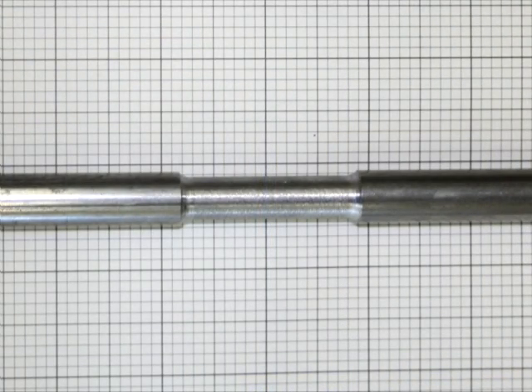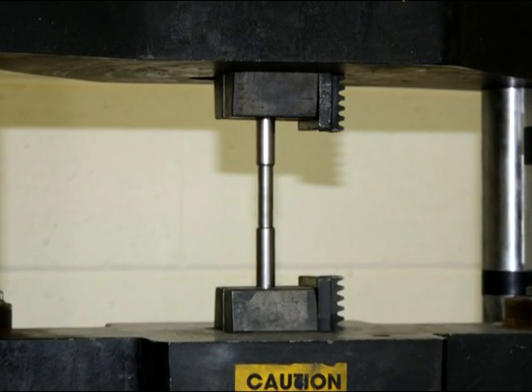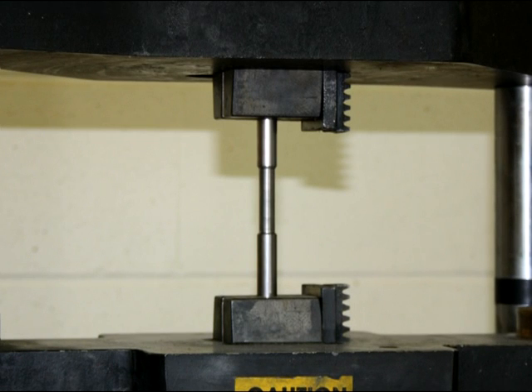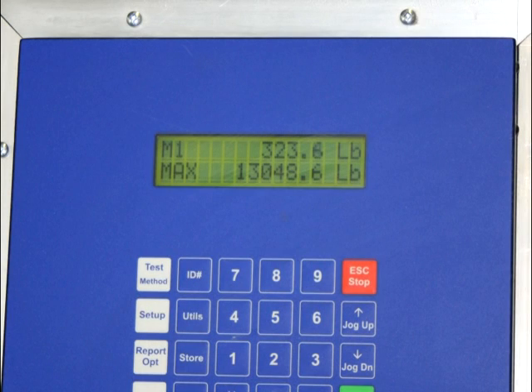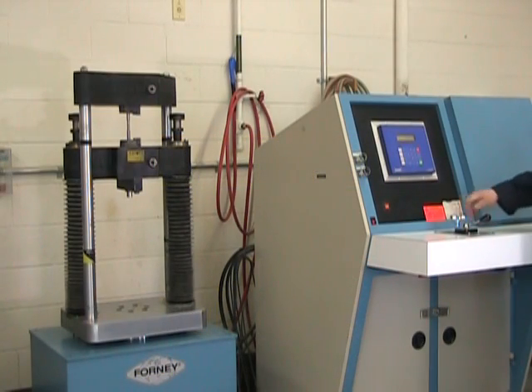Our test part here is a necked and accurately turned piece of mild steel. It's necked or reduced in diameter so that we can predict where the rupture will occur. And its diameter is accurate to help us with our final calculation. In this case, our test piece measures 399 thousandths of an inch in diameter. That means that it is 1/8 of a square inch in surface. Since the final results will need to be in square inches, well, we'll multiply the results of this test by 8. So let's take a look at the test itself.